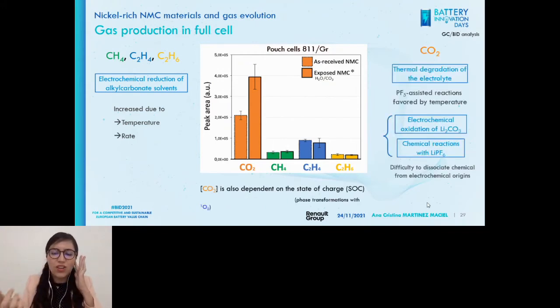On the contrary, CO2 shows a huge difference when NMC exposed or as-received is used. This is because first, there is thermal degradation of the electrolyte, because we did this at 55 degrees. But this shouldn't make this difference, right?